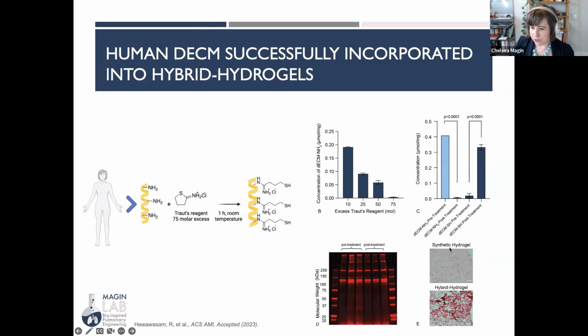So you can see there's a picture down here of synthetic hydrogel that just looks light pink when you stain it with picrosirius red, a stain that highlights collagen fibers. But in the hybrid hydrogel, you can see this much darker red staining that indicates that we have incorporated collagen into the hydrogels. And collagen would be the main component we expect from decellularized extracellular matrix.